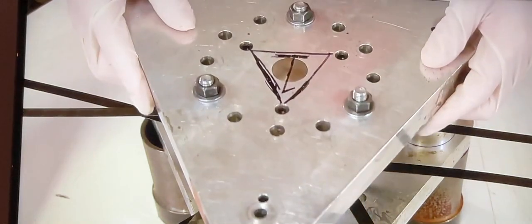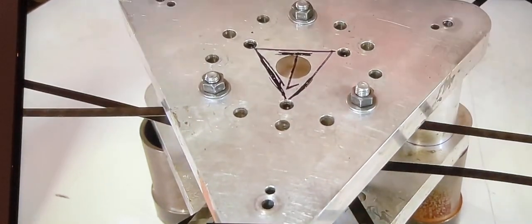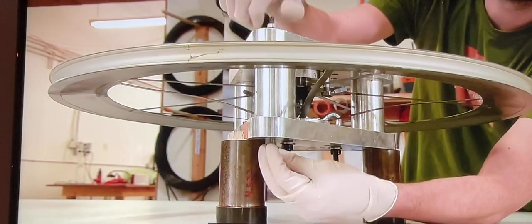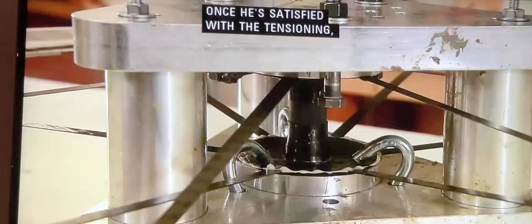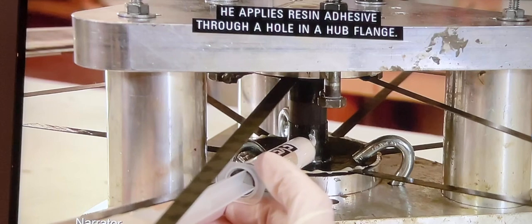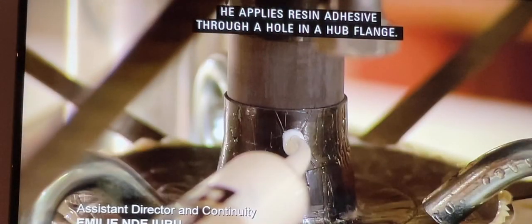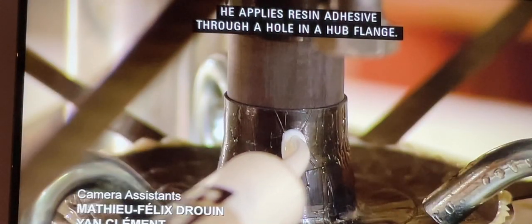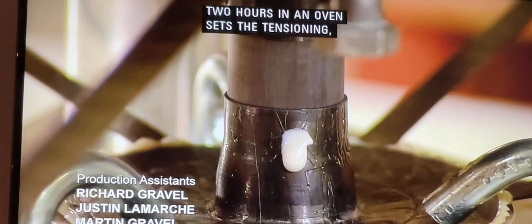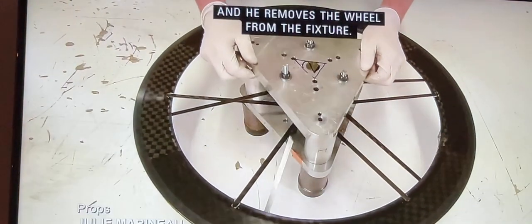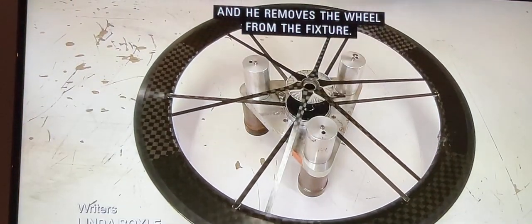The technician locks the bike wheel in a fixture that stretches the spokes slightly. This creates the necessary tension and rigidity. Once he's satisfied with the tensioning, he applies resin adhesive through a hole in a hub flange. 2 hours in an oven sets the tensioning, and he removes the wheel from the fixture.